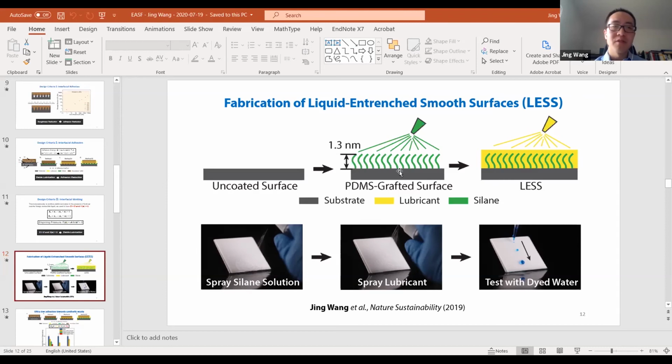But for the longevity, we do observe, not on the toilets, but on the windshield, over not half a year, but over years, that it still degrades. We don't know the mechanism right now, because PDMS should be stable under UV, and we are using brushes made of silicone. So we don't know the mechanism of this degradation, but we think there are some drawbacks of using this one. There's some room to improve. We need more investigation on this.